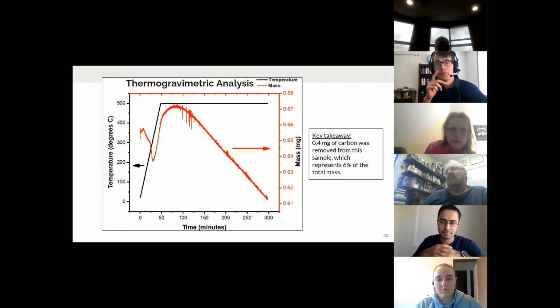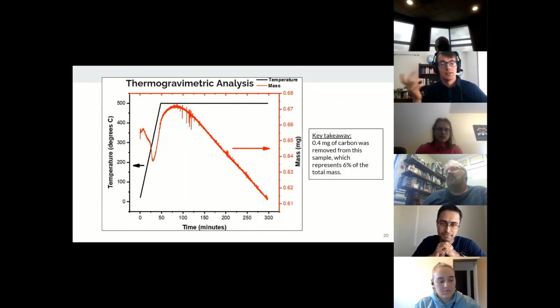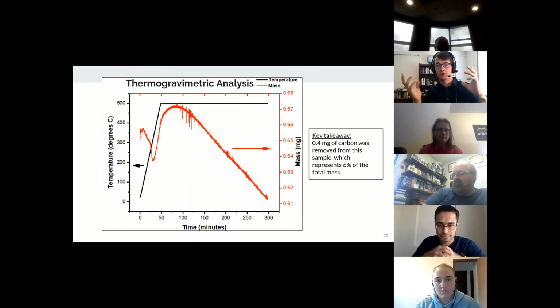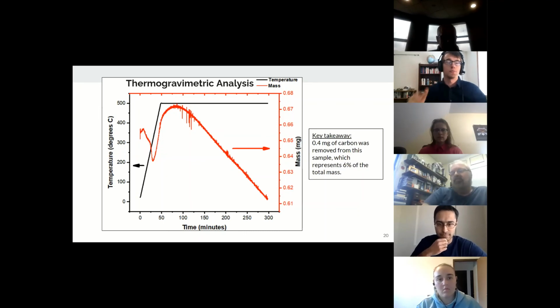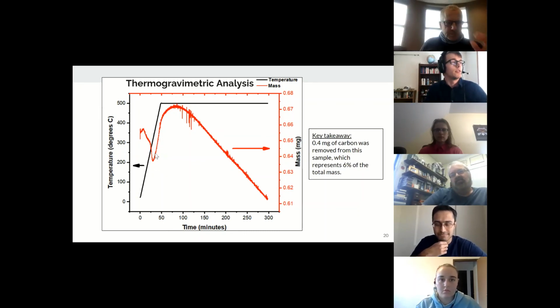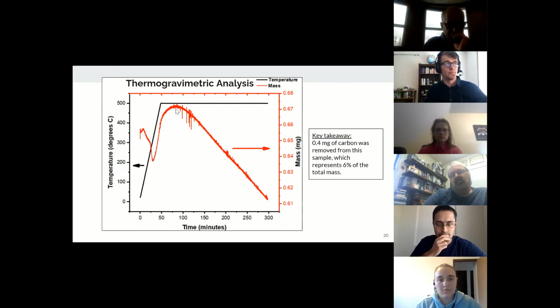Sure, that's an astute observation. To the best of our knowledge, there's a certain amount of precursor that reacted in the reactor, like these carbon groups, and they don't all form versions of carbon that just go straight into the vacuum pump. Some of them are longer chain carbons, and a lot of those will take on oxygen groups. As you heat it up, they'll take on oxygens. Then when you reach the peak temperature, they'll start to burn off that oxygen again as they evaporate. So that's what we've seen.